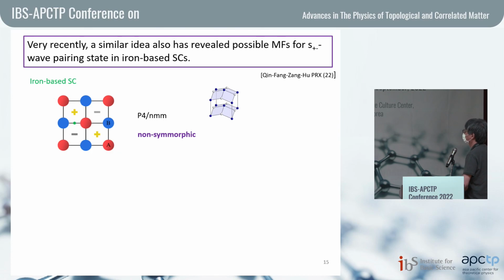And here I show one more example. Very recently, a similar idea has also revealed Majorana fermions for the s plus-minus wave pairing state in iron-based superconductors. Here I show again the crystal structure of the iron-based superconductor. From the top view, we have this kind of crystal structure. The crystal symmetry is P4/nmm. This means that we have inversion symmetry and two different mirror reflection symmetries. Importantly, in this case they have different centers, so the symmetry is non-symmorphic.